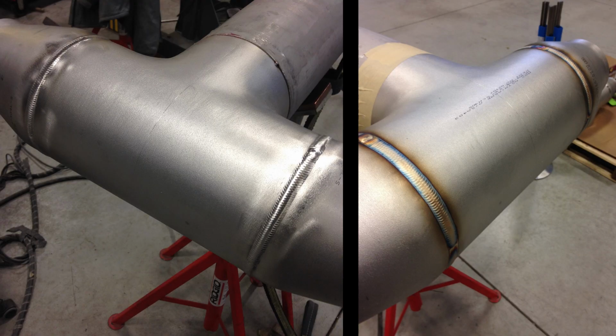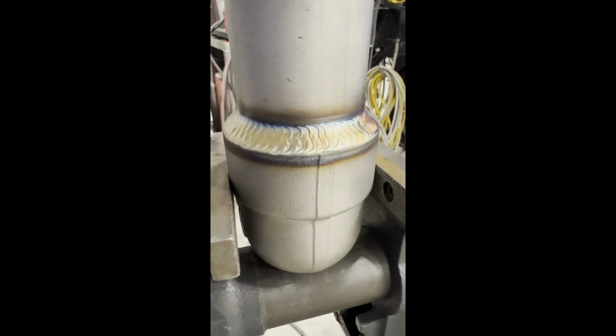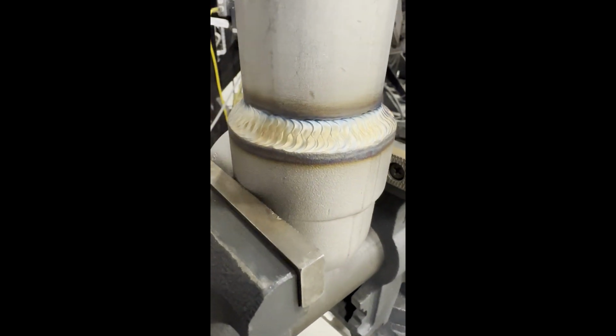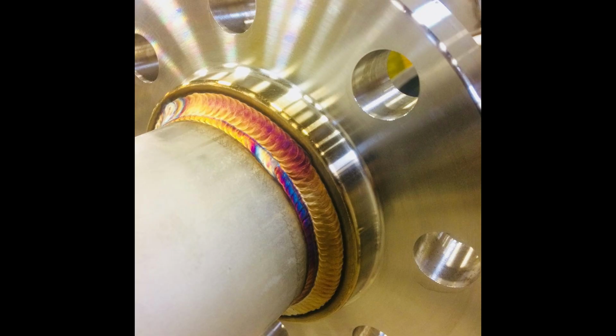It shrinks between 3/32 and 1/8. When I do a pipe weld by TIG, mostly it shrinks 3/32 per each weld joint. Socket welding: it shrinks around 1/16. Sleeve-on flange welding: it shrinks around 1/16 too.